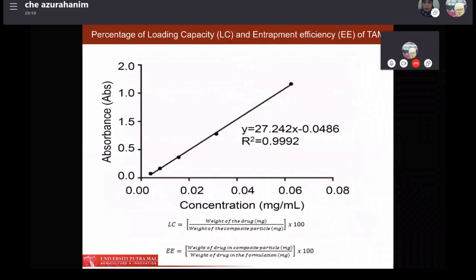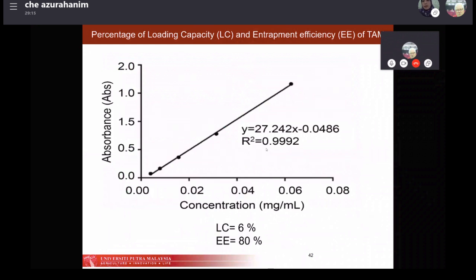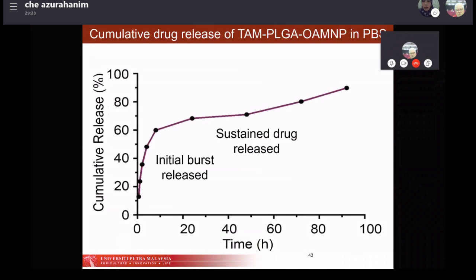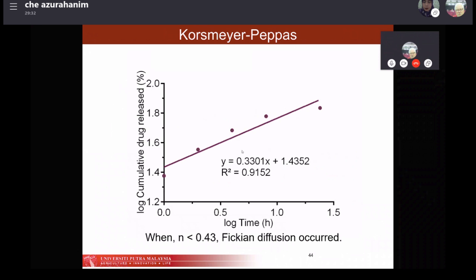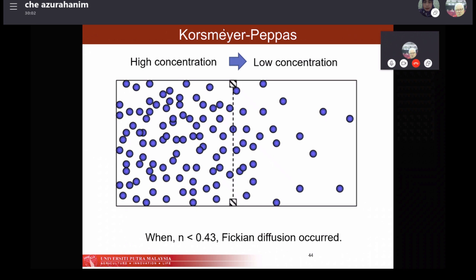We also did a calibration for the percentage of loading capacity and entrapment efficiency of tamoxifen. Based on this graph, we can see that the R squared is about 0.9992, and she also did some cumulative drug release of TAM-PLGA-OAMNP in phosphate buffer saline. She tried to fit the data using several models, and her data fits the Korsmeyer-Peppas model. That means when n is less than 0.43, Fickian diffusion occurs. That means there is some Fickian diffusion of our drug. In terms of the Korsmeyer-Peppas model, that means the drug or the nanocomposite moves from the higher concentration to the lower concentration.